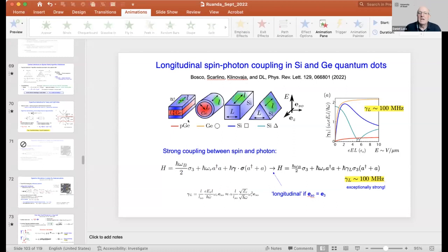Yeah. Okay, so in contrast to electrons, holes have a richer structure connected to the underlying atomistic structure of the material. So as I pointed out, the holes consist of p-wave Bloch wave functions, and these p-wave Bloch wave functions are not spherically symmetric. They are anisotropic, and it's these states which can actually see the atomistic spin-orbit interaction. So there's a relativistic spin-orbit interaction which we get if we go beyond the Schrödinger equation.